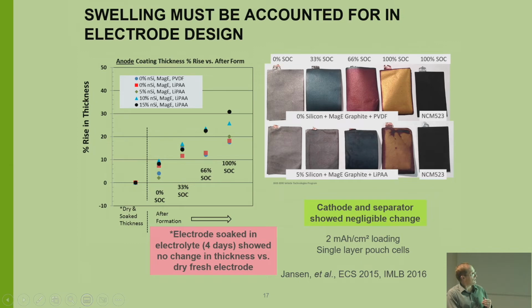But this is a graphite electrode in different states of charge. When you get all the way up to 100% state of charge, and you take the cell apart, it's a bright, shiny yellow brass color. That's just 60 millivolts above lithium potentials. If I hit it with a drop of water, it explodes, because it has very high surface area, and it really wants to react with water. If I add some silicon in there, the color is a little muted, but it's still also very reactive.